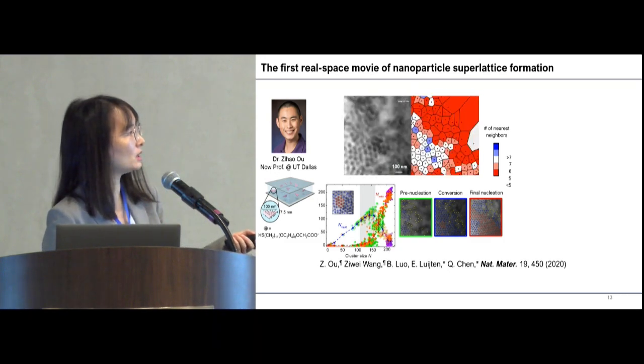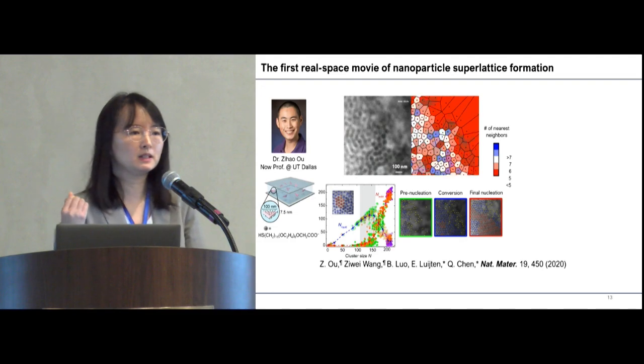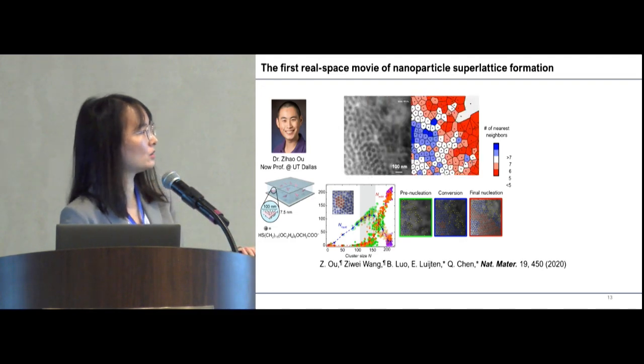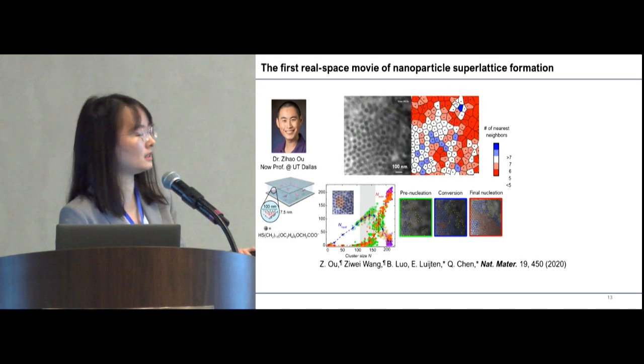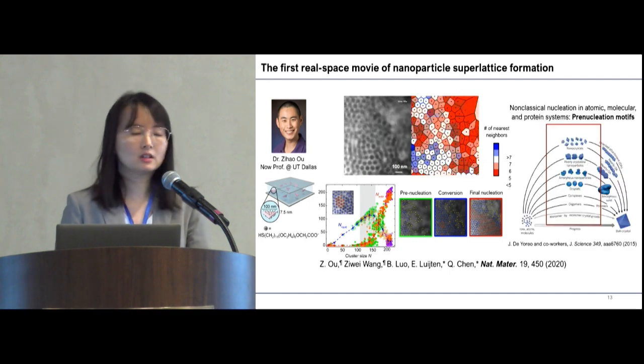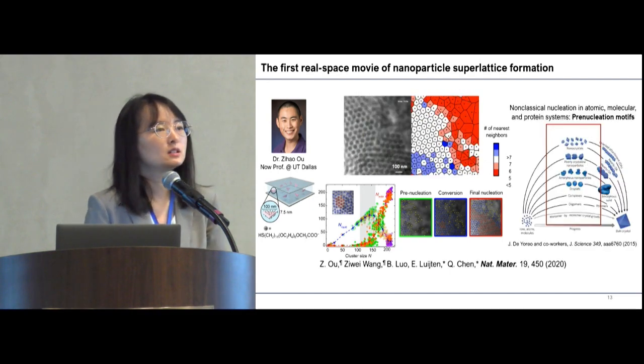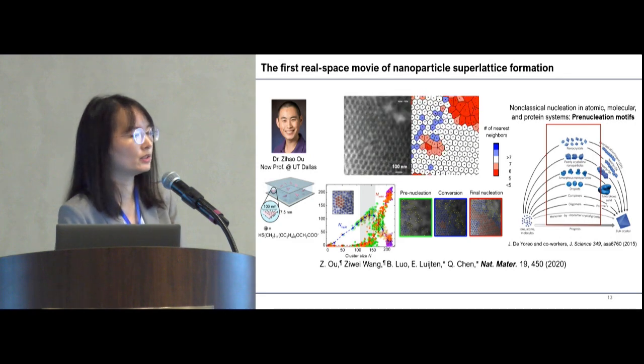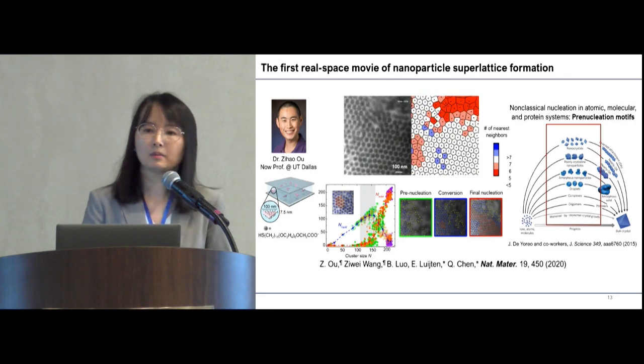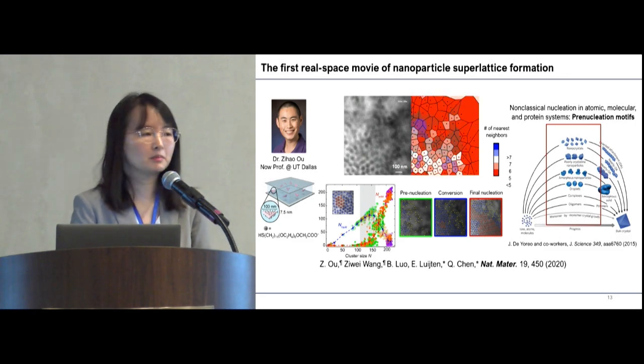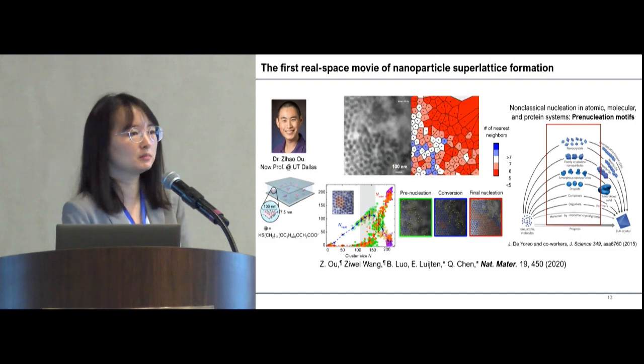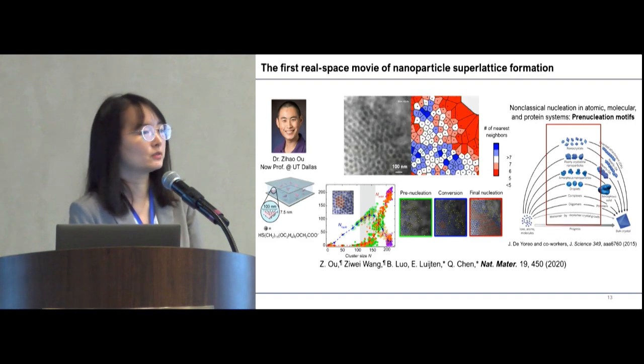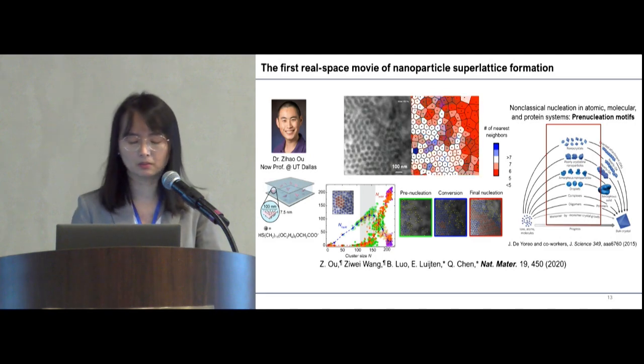We're able to do single particle tracking to follow the position of particles to allow us to chart the crystallization coordinate as shown here. So this actually tells us, in the end, this system goes through this non-classical nucleation pathway. And this is a pathway that has been identified in atomic molecular protein system before. We identified it for the first time for nanoparticle superlattice.